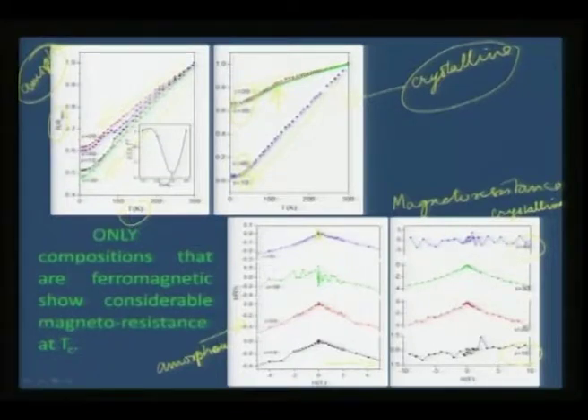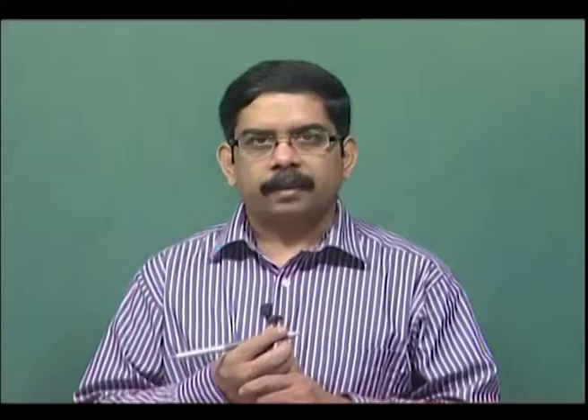non-magnetic phases do not show any magnetoresistance, whereas the 20 and 30% which show a magnetic transition, they respond nicely and they show magnetoresistance behavior. So, this is going hand in hand. Only compositions that are ferromagnetic show considerable magnetoresistance at TC. So, this is a confirmation that there is definitely influence of the size effect when we study the magnetism and electronic property, and you see a systematic change when you go from amorphous alloys to crystalline alloys.